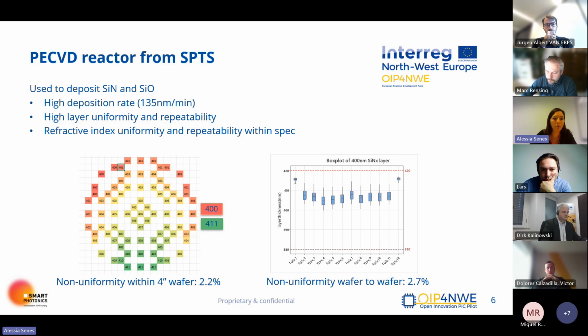Here you see a map with the layer thickness across the 4-inch wafer, and you see that the non-uniformity within the 4-inch wafer is 2.2%. In the second graph, you see the layer thickness of layers deposited on different wafers, so from different runs. And you see also the non-uniformity wafer to wafer is 2.7%, so it's very good.